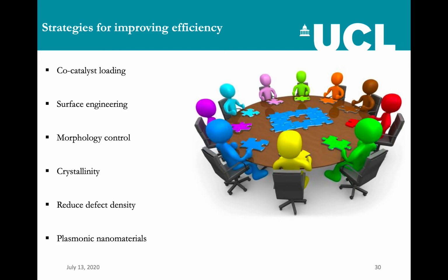This crystallization also reduces the defect sites present inside the material. So we have to reduce the defect density. This is another strategy I mentioned. By improving the crystallinity, one can really control the defect density in the material. These two strategies are interrelated. And this is another important strategy. One has to focus on this, that is the field I was working in at EPFL.